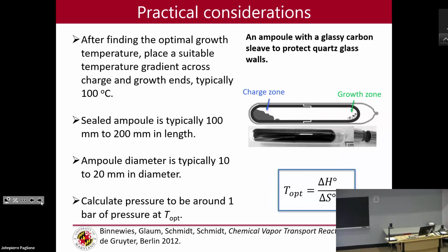So typically, lengthwise, you want something 100 millimeters to 200 millimeters. You want the diameter to be 10 to 20 millimeters. And again, this is the way you're going to find what temperature you're going to do it, okay? So you can do oxides, you can do halides, you can do chalcogenides, you can do other things like black phosphorus perhaps, and other 2D materials this way as well. But it doesn't have to be a layered 2D material. It can be any kind of compound.